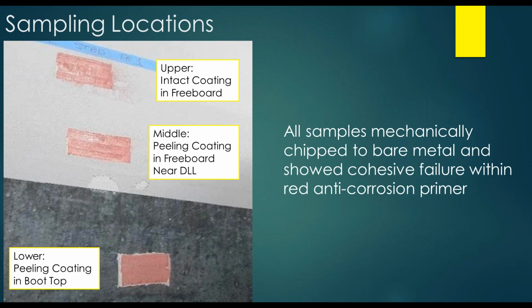Samples were secured from several locations in order to look at the different types of coating systems that were involved. For the upper area, this was an intact coating where there were no adhesion issues. This was taken in the freeboard well above the DLL. In the middle region, we're looking at areas where peeling had been observed, in that band just above the DLL. Finally, in the lower area, we sampled an area of the boot top.